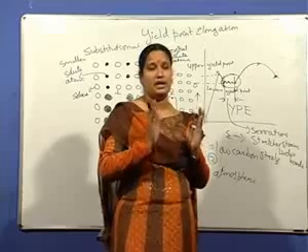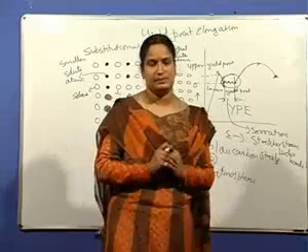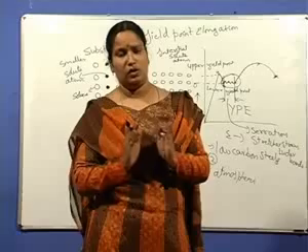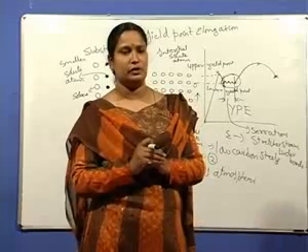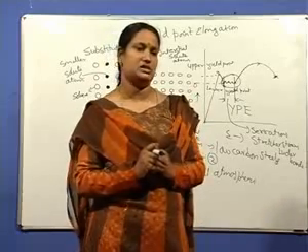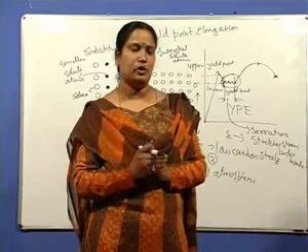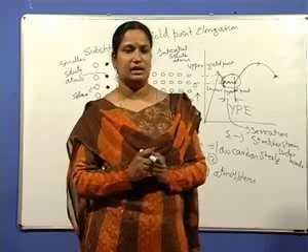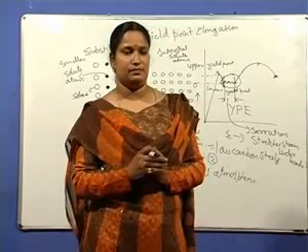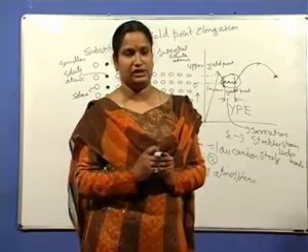They form an objectionable surface on the low carbon steel sheet materials during sheet forming operations for automobile parts. During deep drawing this is seen. This acts as a defect. So this appears as a defect.